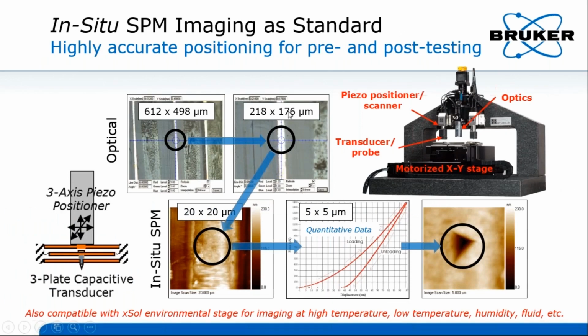By using in situ SPM, scanning probe microscope imaging, we can utilize the same probe used for nanomechanical testing to image the sample surface and obtain high-resolution images from which one can identify and specify the testing locations. It is very important to navigate around a sample about the microstructures and then to avoid roughness before performing nano indentations. On the other hand, after indenting, we can also go back and re-image the sample surface to verify correct indent location. Once the post-image of the indents has been performed and the precise indent location has been confirmed, we can have high confidence that the quantitative data is reliable.